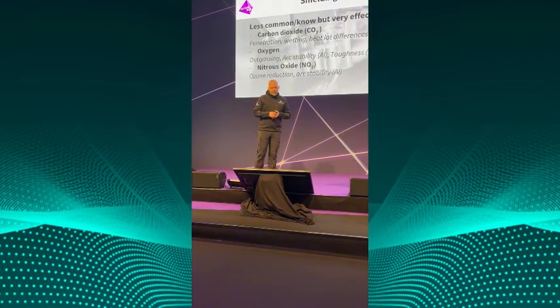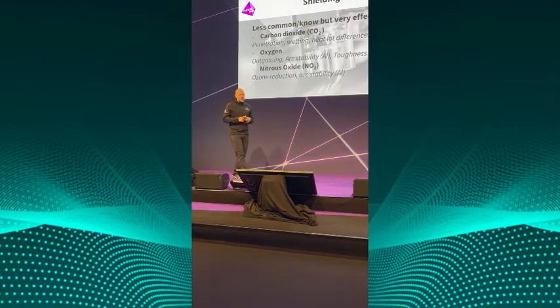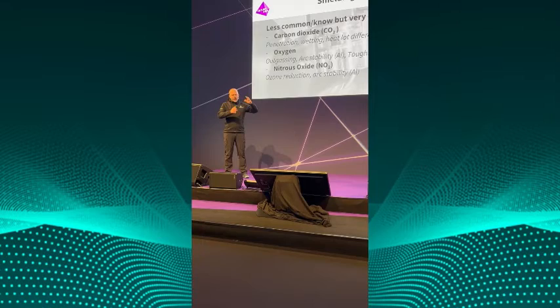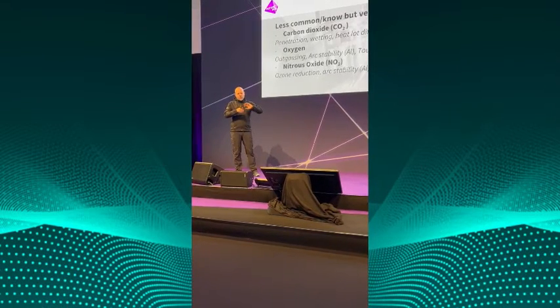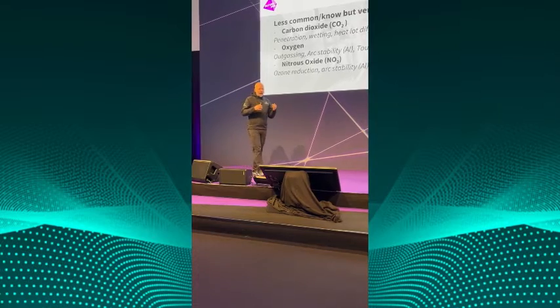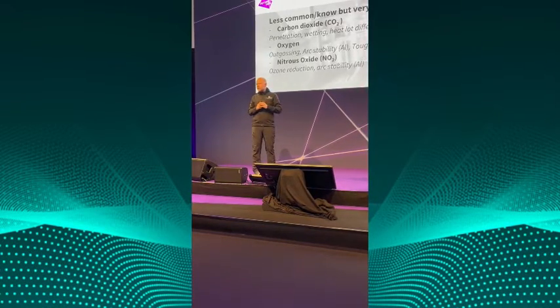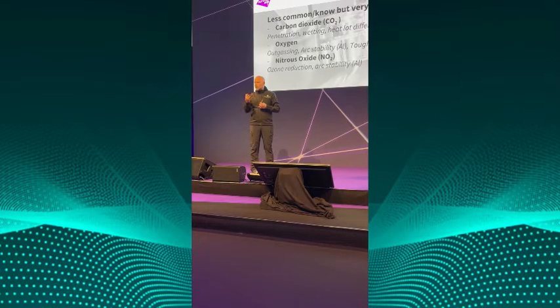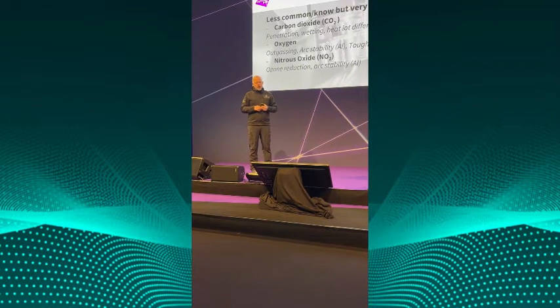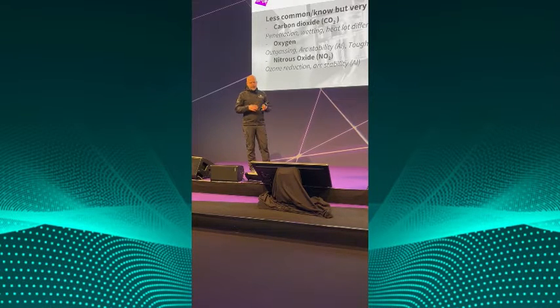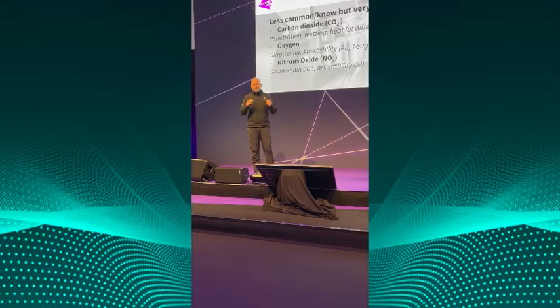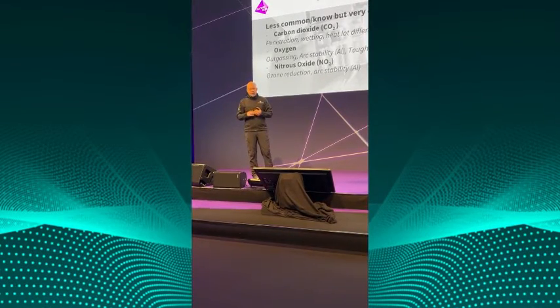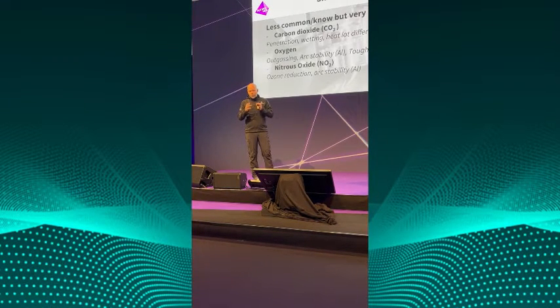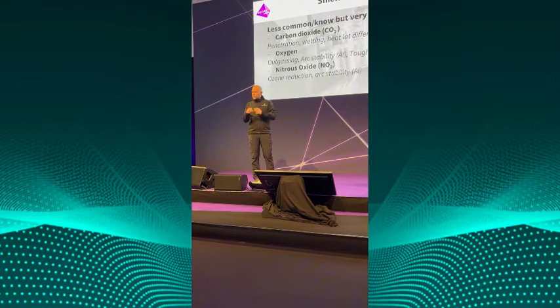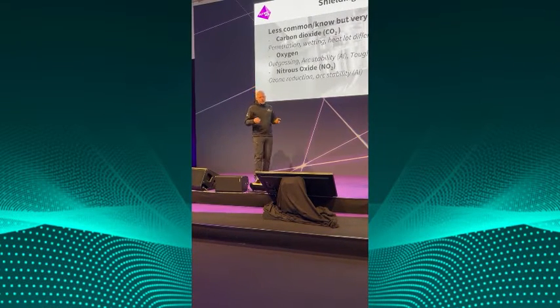A little bit less common component is carbon dioxide, some may have heard about it, but with carbon dioxide you can change the fluid mechanics, the Marangoni flow, so you can have an extensive penetration, like 4 or 5 millimeters in a single pass with the addition of carbon dioxide. It increases the wetting in fillet welds, but can also be used to compensate for different heat loss, like sulfur content, in low amounts, more in the parts per million region. So welders or companies which weld, like flanges to tubes, can compensate for different heat loss.